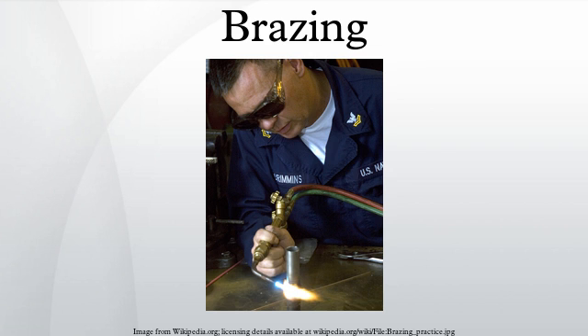On wetting, brazes may liberate elements from the base metal. For example, aluminium-silicon braze wetting silicon nitride dissociates the surface so it can react with silicon, and liberates nitrogen, which may create voids along the joint interface and lower its strength. Titanium-containing nickel-gold braze wetting silicon nitride reacts with its surface, forming titanium nitride and liberating silicon. Silicon then forms brittle nickel silicides and eutectic gold-silicon phase. The resulting joint is weak and melts at much lower temperature than may be expected.